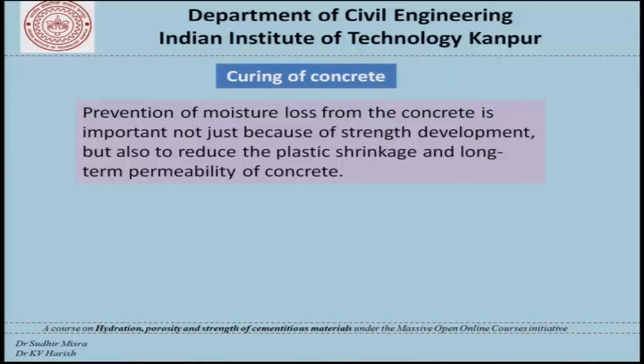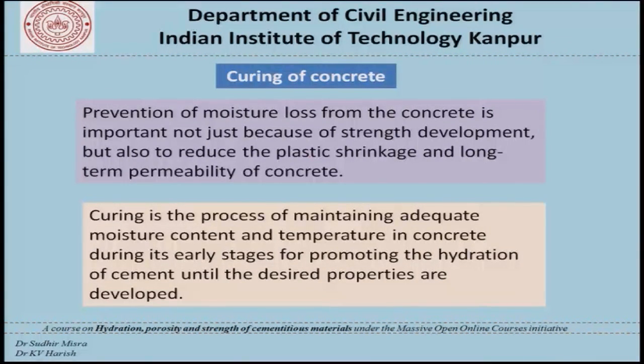Prevention of moisture loss from concrete is important, not just because of strength development, but also to reduce the plastic shrinkage and the long-term permeability of the concrete. And therefore, we can define curing as the process of maintaining adequate moisture content and temperature in concrete during its early stages for promoting the hydration of cement until the desired properties are developed.